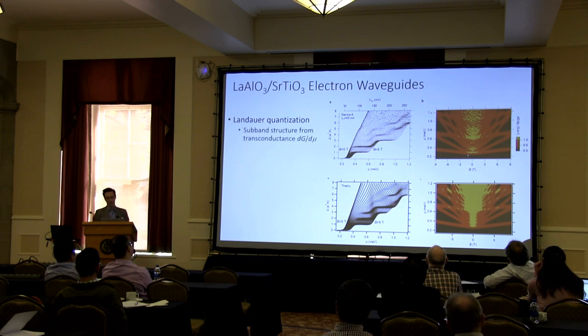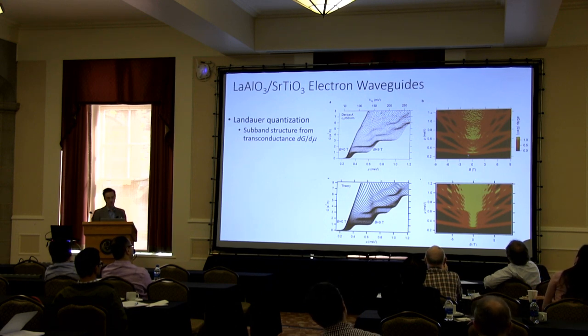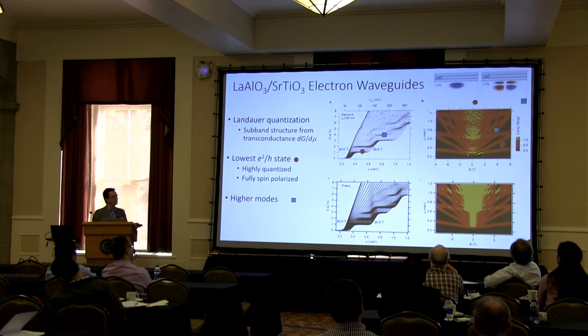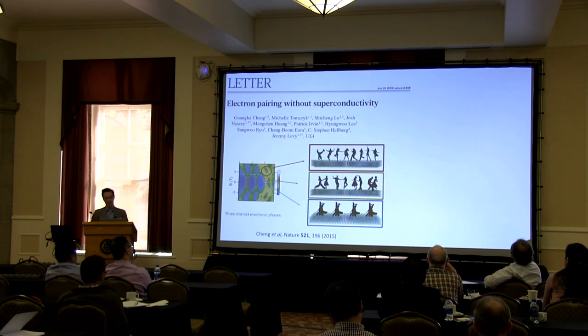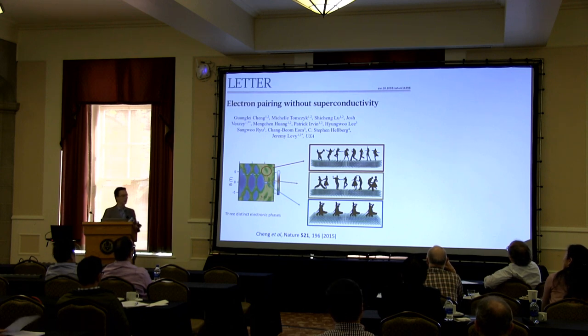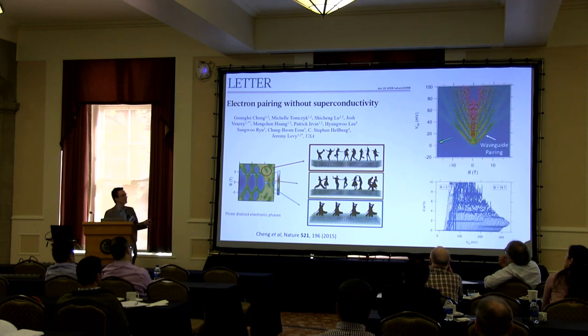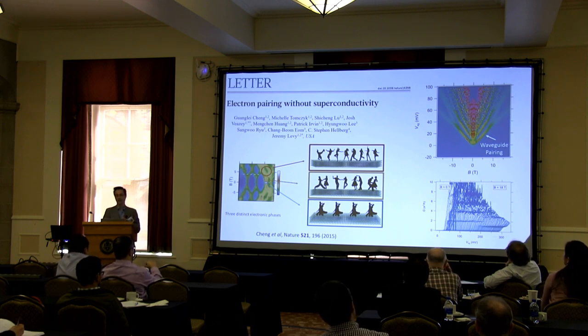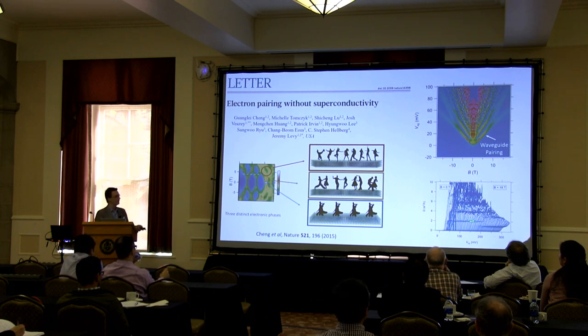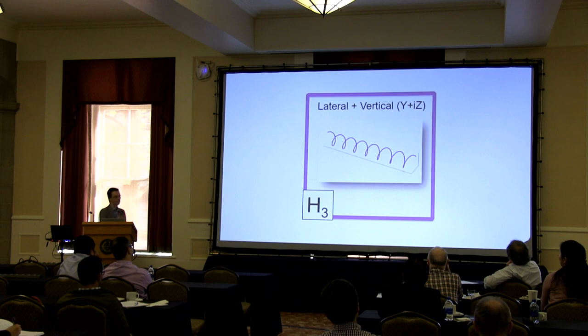However, there are some subtle differences between the theory, which is on the bottom, and the experiment, which you see on the top. So experimentally, what we find is that actually these lines don't meet at zero. They meet at something called the pairing field. So we also know that there's a very strong attractive electron-electron interaction, which leads to a paired ground state, which is not superconducting. And so another example that you see here is basically this line here, which up to about 8 tesla, electrons are paired together, and then they split apart. And you can see that in the quantized conduction going from 2e squared over h in the paired state to 1 and 3. This is actually reentrant pairing. So this is important for what I want to tell you about now.